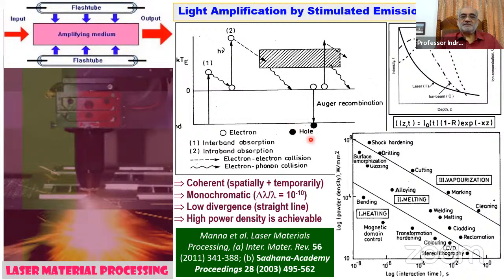And this is an extremely fast process because, for direct band gap or indirect band gap materials, or no band gap materials like metals, the excitation of the electrons to the higher energy state and falling back to the ground state, and in the process absorbing the incident photon energy and converting that into lattice heat, is possible only within less than a nanosecond, between nanosecond and picosecond. So it is an extremely fast heating and cooling process.